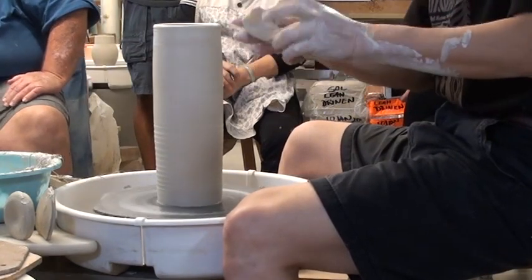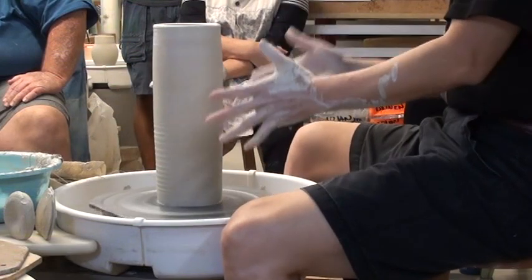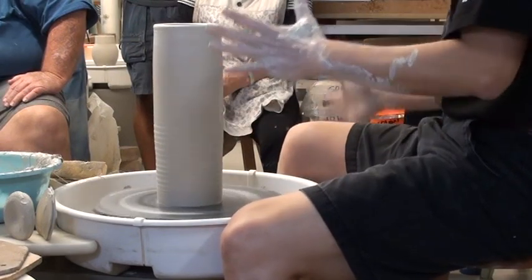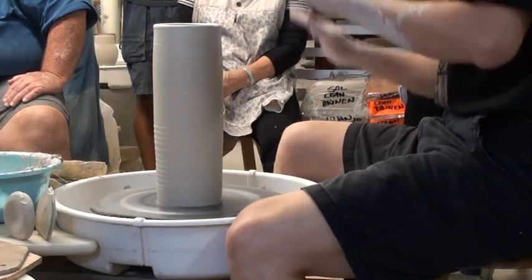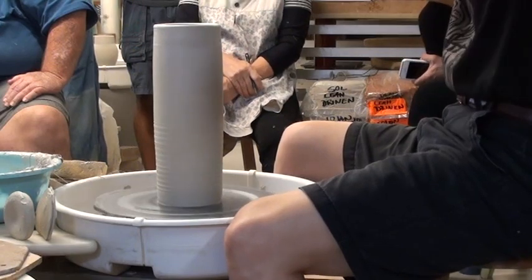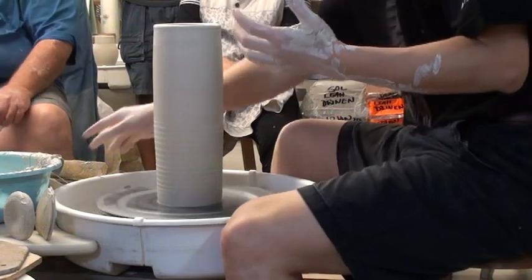Yeah, I put the sodium silicate and then I will torch it. So the inside is still wet, but the outside is dry. And the sodium silicate is going to bond on the clay. The sodium silicate is kind of like a glass, a liquid glass. But once it dries, it bonds. And then when you stretch, it just cracks. So you get a very nice texture.